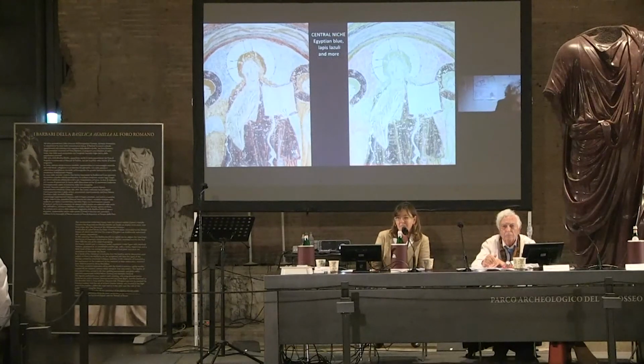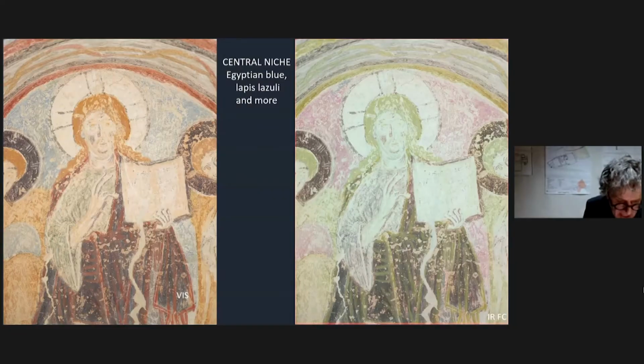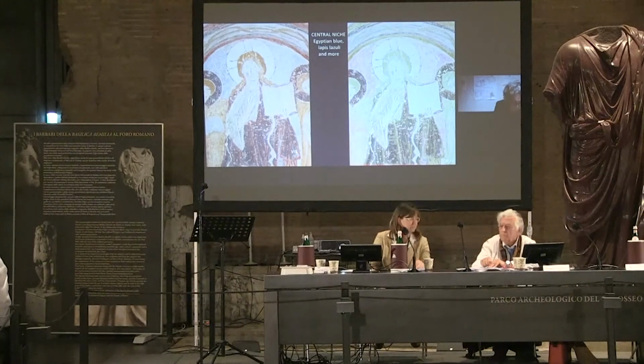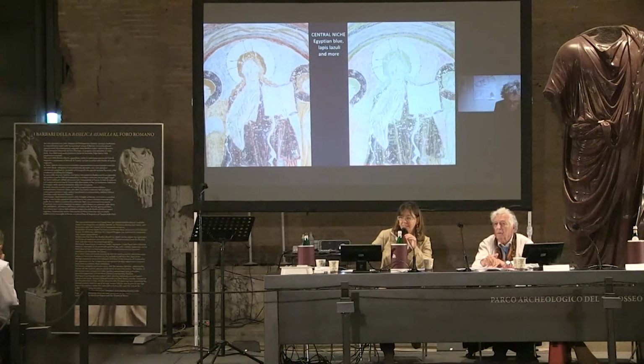Just a few words. In summary, for what concerns Mals, the first analysis hardly reads the presence of Egyptian blue in the Mals fresco, in the blue backgrounds or gray-blue shadows and superficial white glaze. Raman shows the prevalent presence of lapis lazuli, but with a non-pure spectrum, which predicts the presence of another component compatible with Egyptian blue. XRF analysis reads the presence of copper pigment at the point where lapis lazuli is witnessed. Multispectral imaging confirms the presence of Egyptian blue and lapis lazuli with a striking overlap between them, probably a significant sign that they have been applied together.